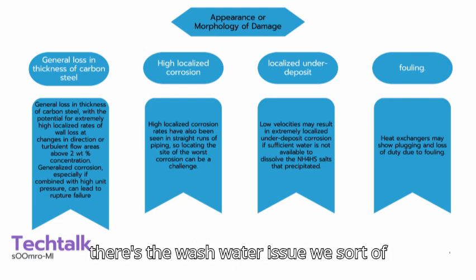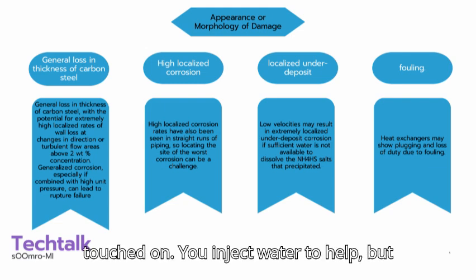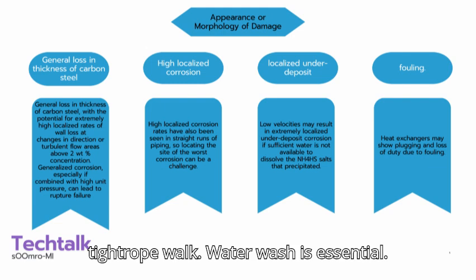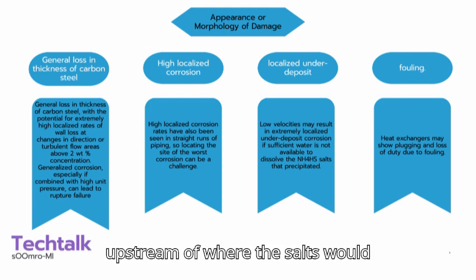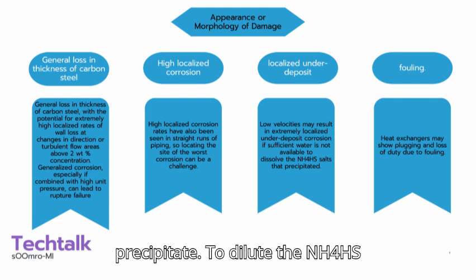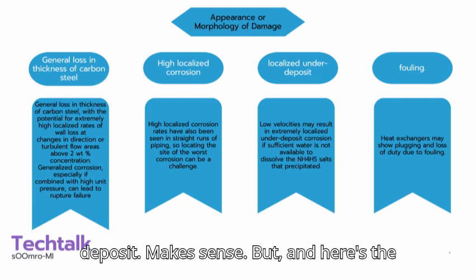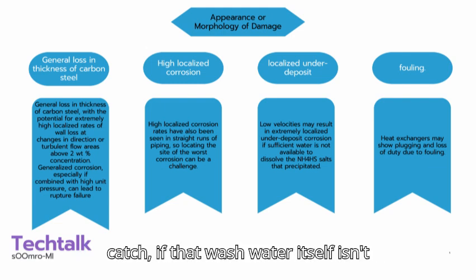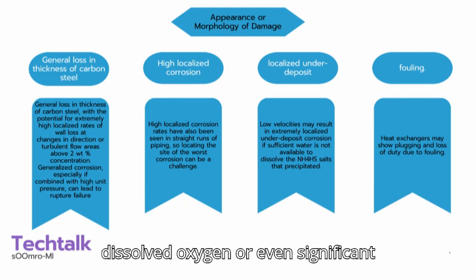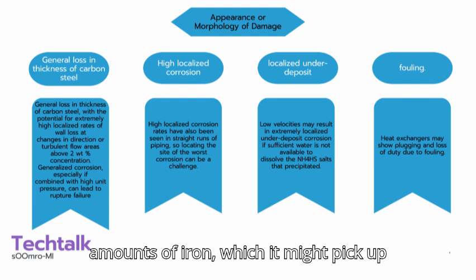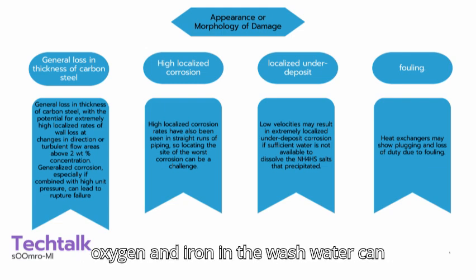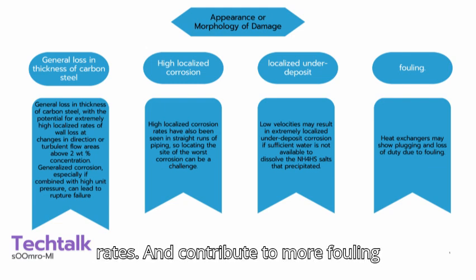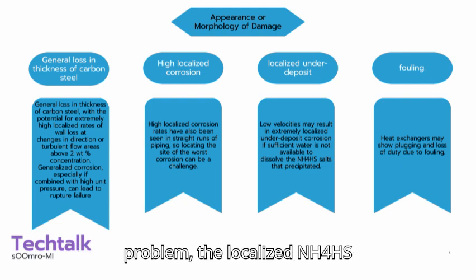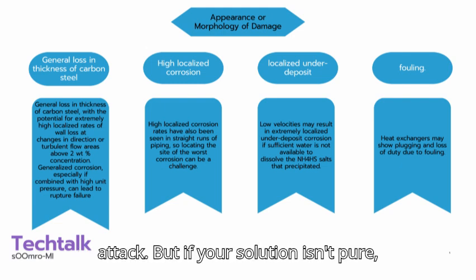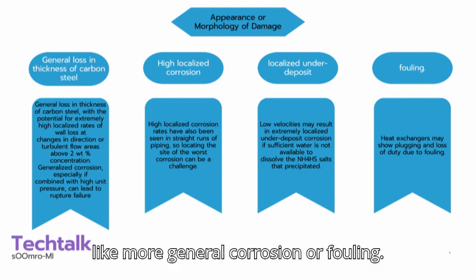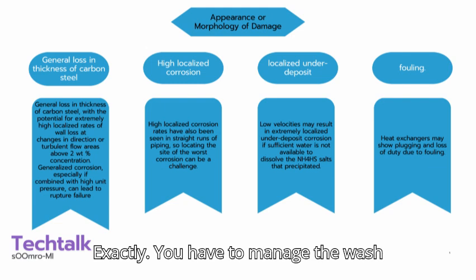Wow. Okay. And then there's the wash water issue we sort of touched on. You inject water to help, but it can also hurt. That's the paradox, the tightrope walk. Water wash is essential. You have to inject water, usually upstream of where the salts would precipitate, to dilute the NH4HS and flush the salts away before they deposit. Makes sense. But, and here's the catch, if that wash water itself isn't properly treated, if it contains dissolved oxygen or even significant amounts of iron, which it might pick up somewhere else in the system, that oxygen and iron in the wash water can actually increase the general corrosion rates and contribute to more fouling downstream. So you're trying to solve one problem, the localized NH4HS attack, but if your solution isn't pure, you could be creating another problem, like more general corrosion or fouling. Exactly. You have to manage the wash water quality very carefully.